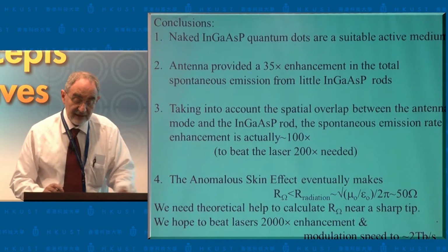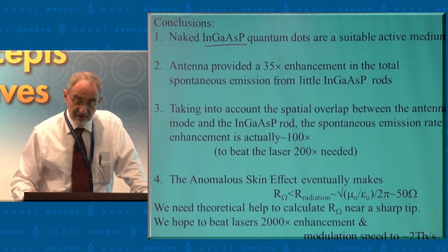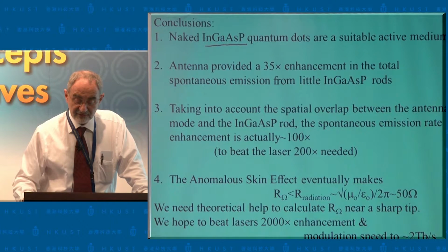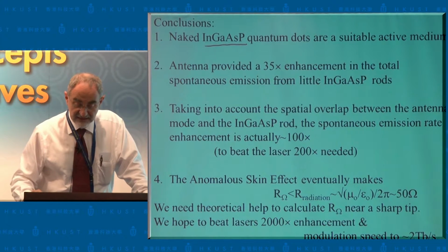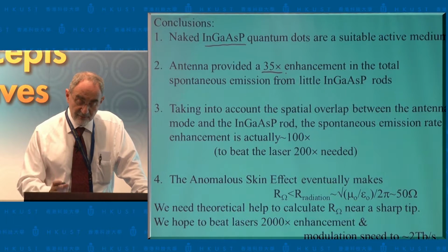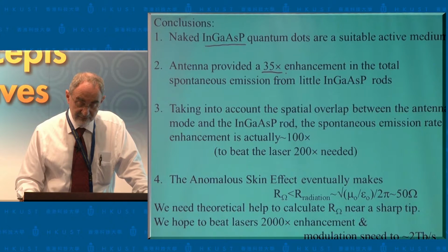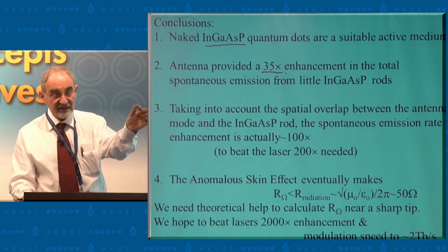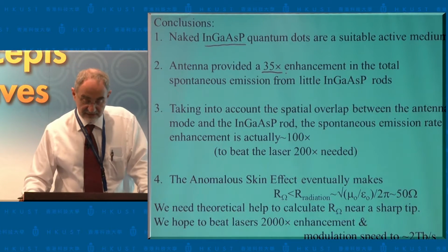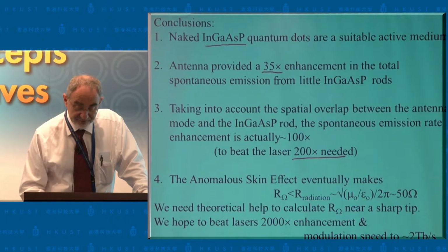So let me conclude: it seems like these particular quantum dots make it really easy to do the work because they're just little islands. We have demonstrated so far 35 times enhancement. I should say we've made steady progress. Last spring it was 25 times. So we've definitely improved things. As we make that spacing narrower, we'll get more enhancement. The big question: can we really beat the laser?